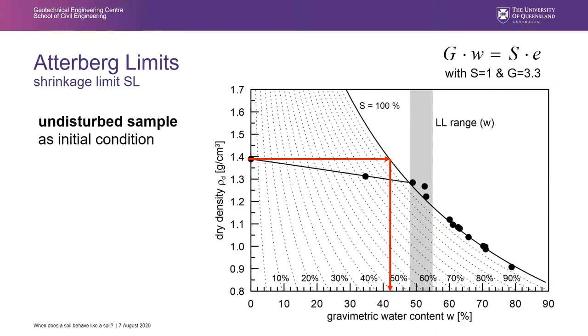So now I've shown here where the liquid limit range is. It is at a higher water content, and the plastic limit range at a lower water content, and the shrinkage limit is in between. This already shows that tailings have a very particular kind of behavior, because we don't normally see this if we look at soil, where the distribution goes from the highest water content, liquid limit, then plastic limit, and then shrinkage limit. I will show this later in other graphs as well, that we have a very particular behavior of tailings.